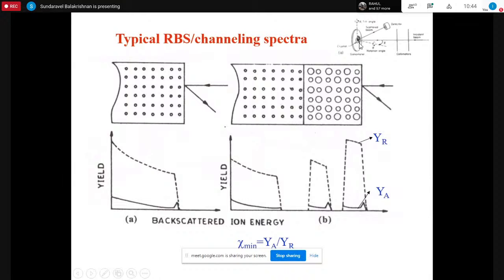The only difference is that our sample is mounted on a goniometer, where the crystal can be tilted about the beam axis, as well as rotated about the beam axis. And we find the alignment condition. Once the beam is exactly aligned, then there will be a drastic reduction in the backscattering.